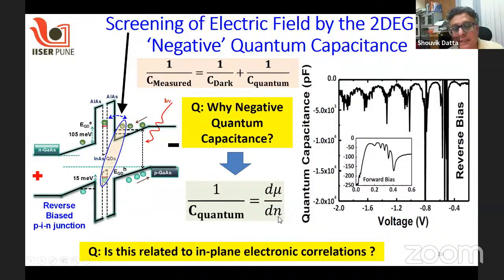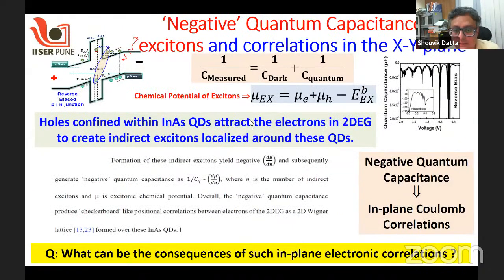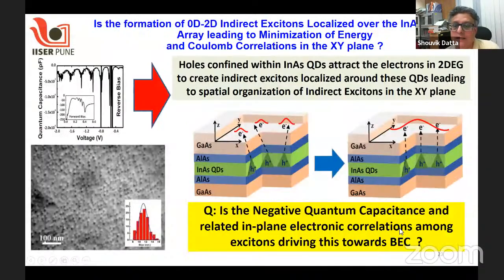Now, quantum capacitance is usually defined as the derivative of the chemical potential with respect to the number of charges. Now, if that is negative, obviously the next question is related to in-plane electronic correlation. Usually the chemical potential of excitons is decreased whenever there is a formation of excitons, because the binding energy reduces the chemical potential of excitons. And so in a way, we tried to explain whether the negative quantum capacitance that you see is leading to in-plane Coulomb correlation. And we know that can happen because the holes in the indium arsenide quantum dots can attract the electrons in the 2DEG. As a result, some of these electrons can get captured as an exciton by these quantum dots.